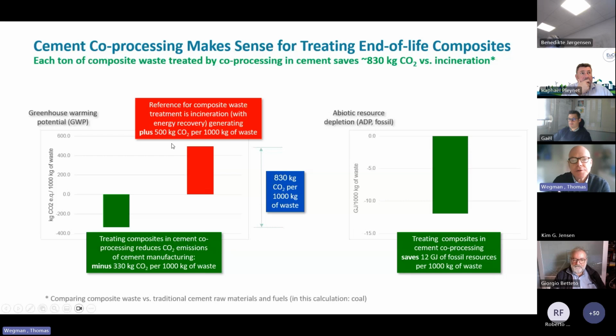If we look at the results, you can see in this graph that if you use glass reinforced composite materials in making cement, it is possible to save CO2. The number is 330 kilograms on average, and when I say on average, it is the average of 3 different material profiles. I'll come back to that in a minute. It's a fair amount of CO2 savings per ton of composite waste.